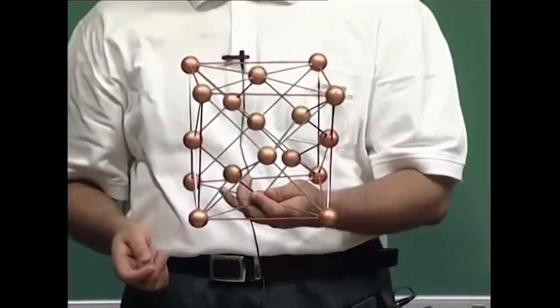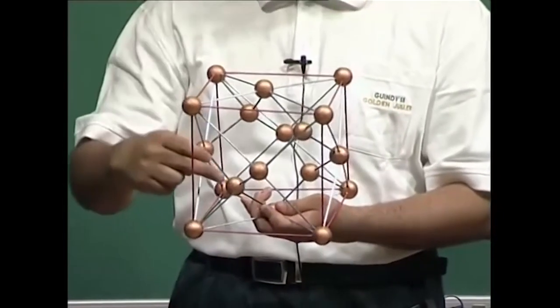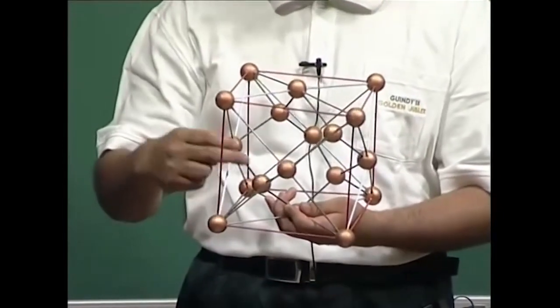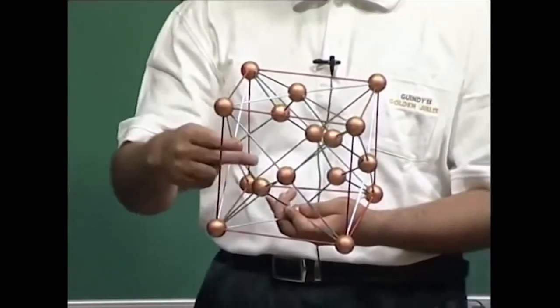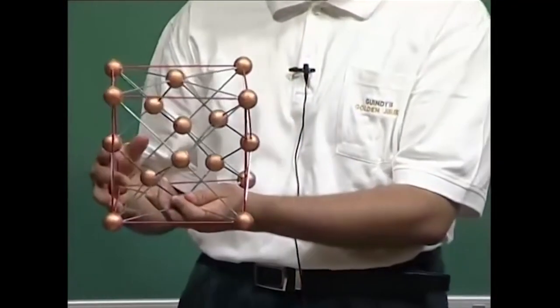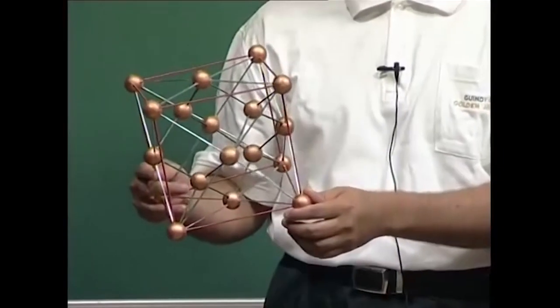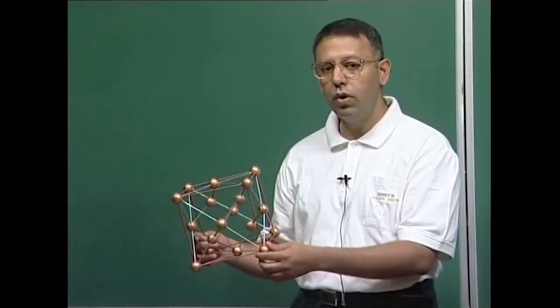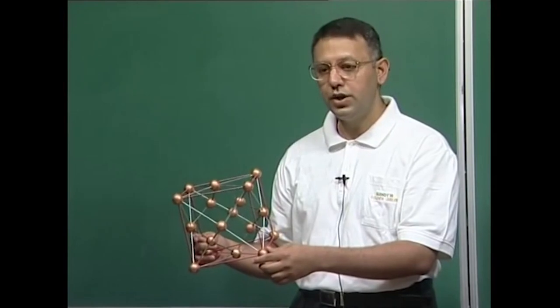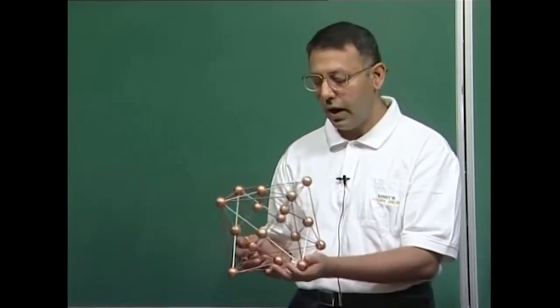If you see how the atoms touch here, they actually touch along the ⟨111⟩ directions, but the touching does not propagate in a straight line — it bends off into tetrahedral angles. Therefore there is no single direction which is a close-packed direction. The conventional unit cell of the diamond cubic structure is based on the FCC lattice and has four lattice points per cell, each occupied by two carbon atoms.